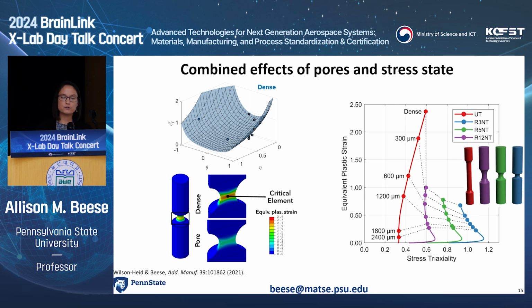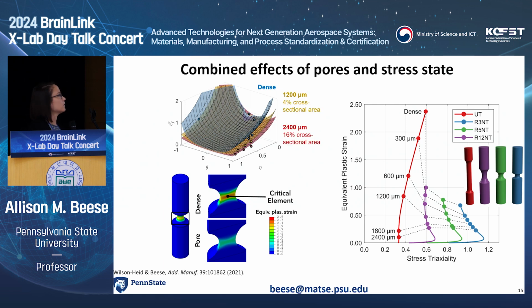So what we can do is say, okay, now we have an understanding that when we have pores of certain sizes, we're reducing our ductility, and we can recalibrate our 3D fracture loci as shown here. So this is showing now what our ductility would be if we had 4 or 16% cross-sectional area loss with a pore. So our ductility drops and our fracture surface flattens out. So how do we use this?